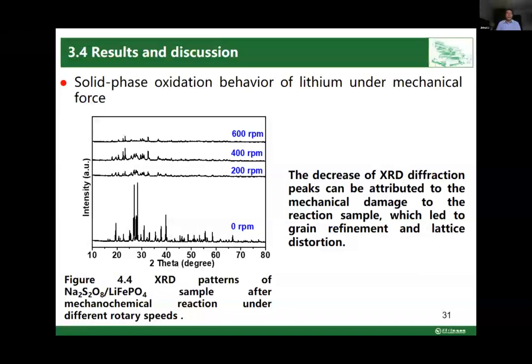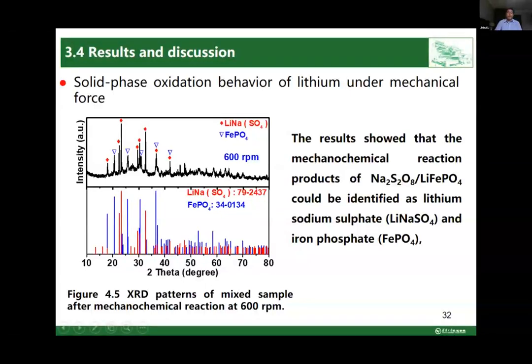The decrease of XRD diffraction peak can be attributed to the mechanical damage to the reaction sample, which led to grain refinement and lattice distortion. So here also shows the XRD pattern of the sodium persulfate/lithium iron phosphate sample of the mechanical reaction at 600 RPM. So here is the result.